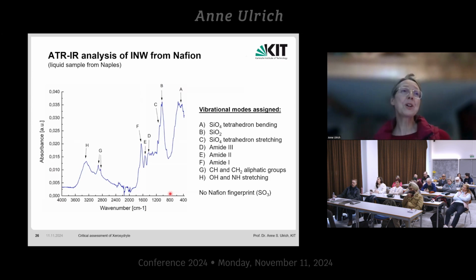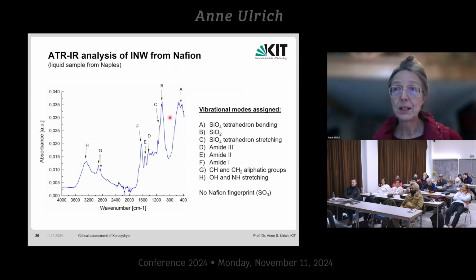Right. To be sure that our analysis of organic matter and silica shells was correct, we did some attenuated total reflection infrared analysis of the fluid sample from Naples, prepared by Nafion, which had no starting material contamination. And we see here all the stretching and bending vibrations of silicate tetrahedra, of amide bonds, characteristic of proteins, and of aliphatic groups, possibly also some fats and amino acids. But interestingly, we could confirm there was no Nafion fingerprint vibration, which is of the sulfonyl groups.